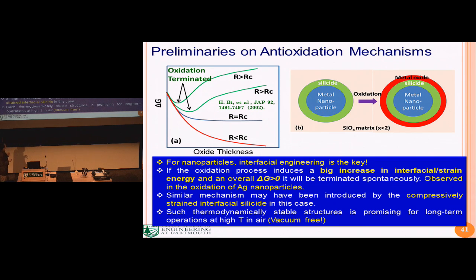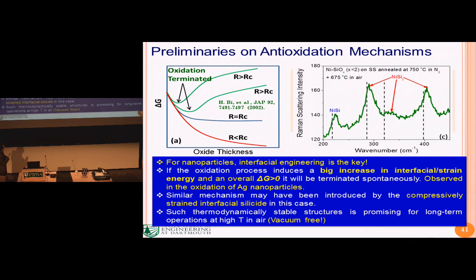It's great for the stability of the system. And we think that probably we're having a similar case, especially since we have a silicide around. And from the Raman analysis, we find there's even strain in the silicide layer. So the increase in strain energy could also prevent further oxidation.